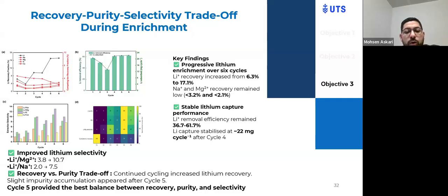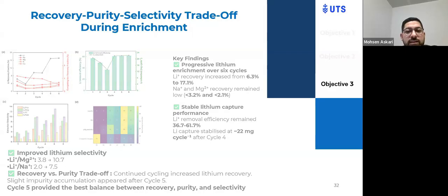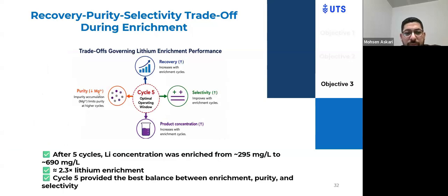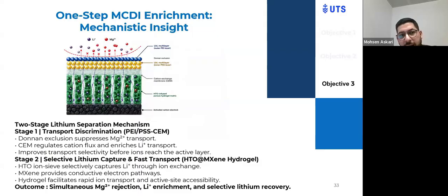As a result, cycle 5 provided the best balance between recovery, purity, and selectivity, in which it enriched the lithium from 294.5 milligram per liter to about 690 milligram per liter, about 2.3 times lithium enrichment. So 5 cycles of this MCDI can give a good balance between enrichment, purity, and selectivity. The result is a one-step fast MCDI process in 5 cycles that has 2 stages.